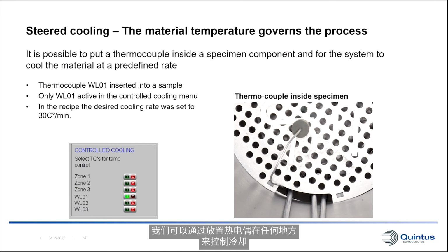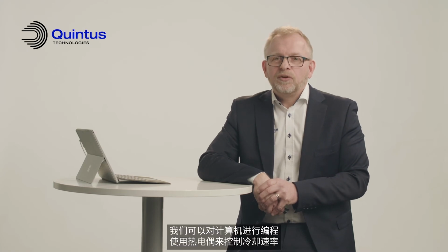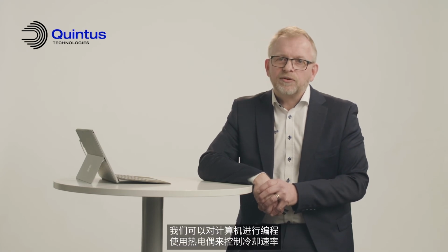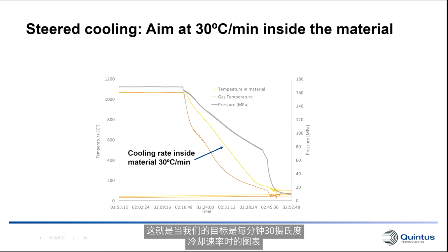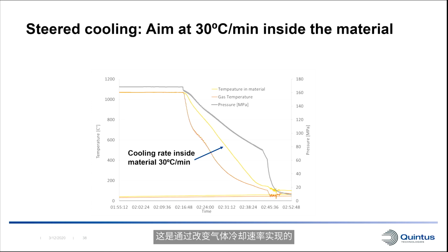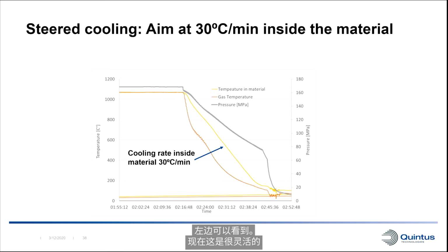We can steer the cooling by putting a thermocouple wherever you want, in a dummy part if you want, or in an actual part if there's a hole for the thermocouple. And based on this, the gas cooling rate, we can program the machine using this thermocouple to steer according to that cooling rate. And this is what a graph can look like when we're actually aiming at a 30 C per minute cooling rate, which is achieved then by varying the gas cooling rate,